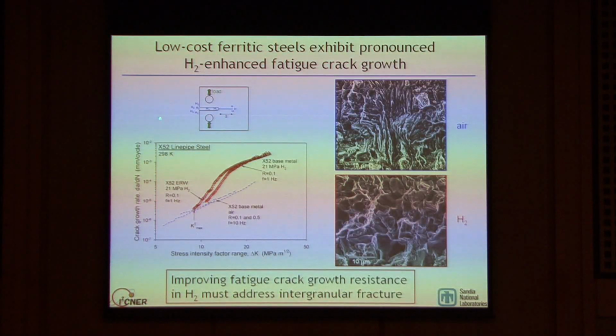I'm showing you some data here, very similar to what Professor Ritchie showed this morning, but this data was just generated in the last few months at Sandia National Laboratories, using a capability we have for testing materials in high-pressure hydrogen gas, much like those here at Kyushu University. I'm showing a plot of crack growth rate - the amount the crack grows per stress cycle or pressure cycle - versus the stress range, or as Professor Ritchie introduced, the stress intensity factor range. We do this testing on model coupons extracted from materials where we can conveniently apply loads and measure displacements.